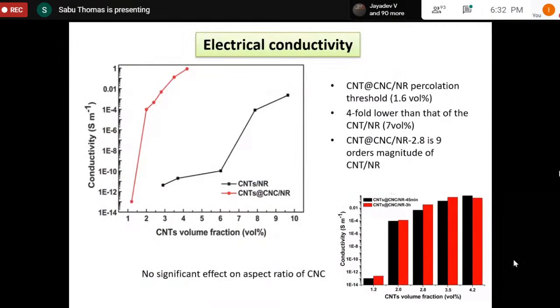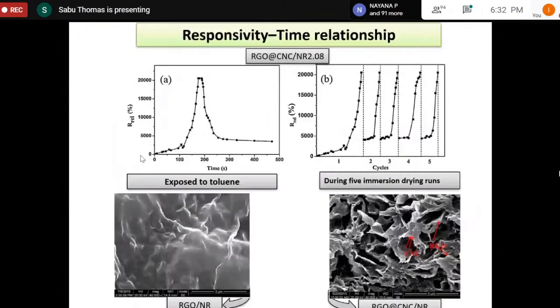I will show you a very interesting slide. You see, if you look at the electrical conductivity of this rubber nanocomposite filled with carbon nanotube and nanocellulose. If you use only carbon nanotube, you get a percolation after adding 6 volume percent of CNT. You get a beautiful percolation. But if you combine nanocellulose and CNT together, look at this. The percolation shifted. This is the combination of nanocellulose and CNT together. You can make conductive rubbers. Let me show you another interesting slide.